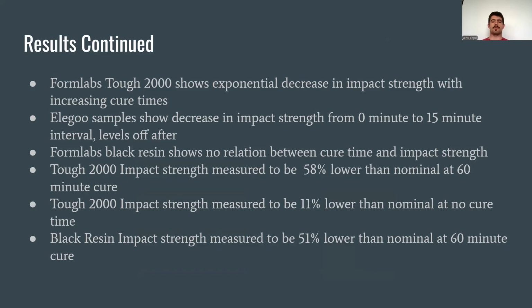The recorded IZOD value for Tough 2000 at a 60-minute cure time was 58% lower than the Formlabs number, and the no cure value was still 11% lower than the Formlabs reported value. The IZOD value for the black resin at a 60-minute cure was also 51% lower than the Formlabs reported value. This shows that we are not achieving values in line with professionally conducted experiments, rather values which give relational results